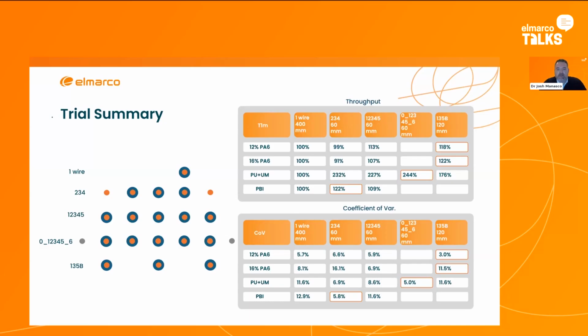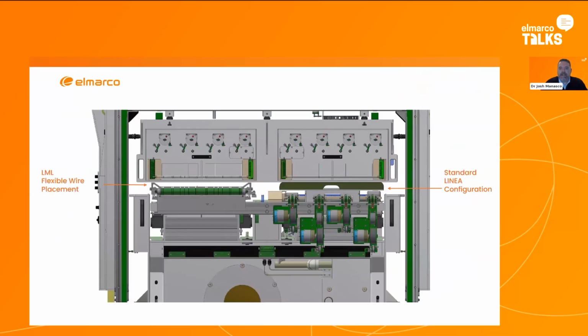And then we were looking to see, do we really sacrifice the coefficient of variation for the basis weight of this material? And we see that for this polyurethane system, we can still get a much higher throughput, but without sacrificing really the coefficient of variation for these materials. So we wanted to implement that on our industrial line, which we've done.